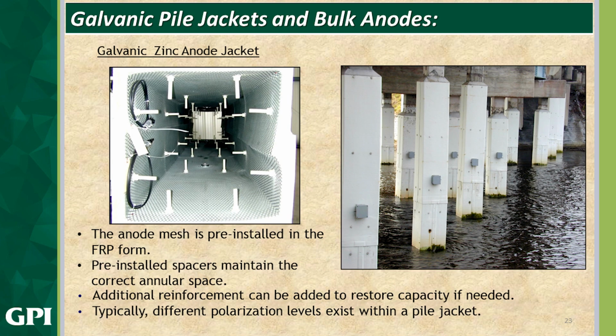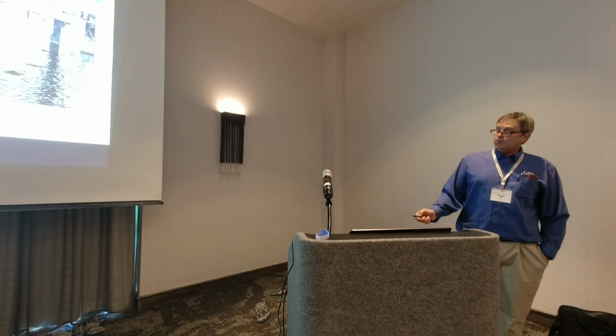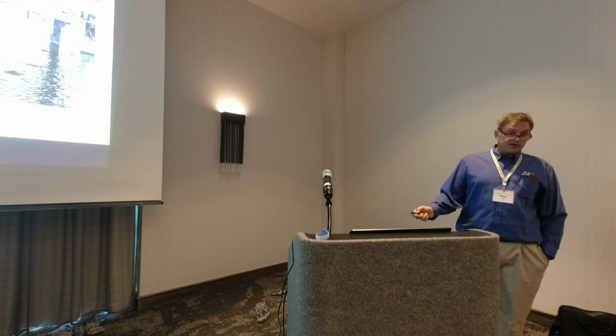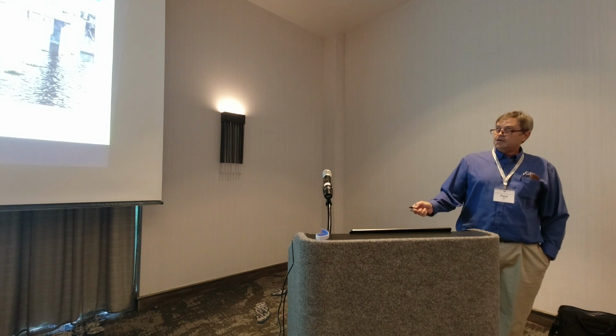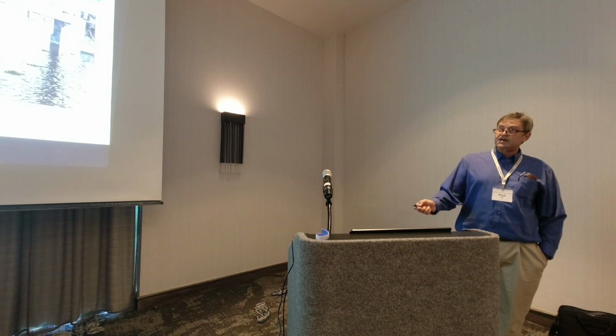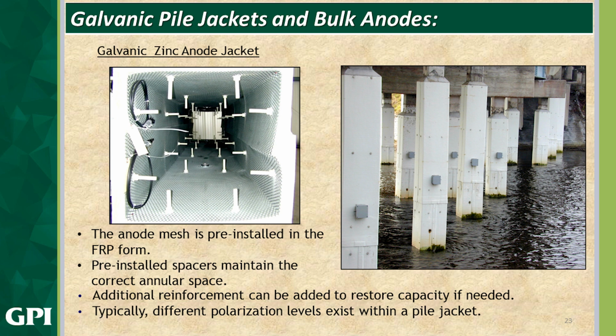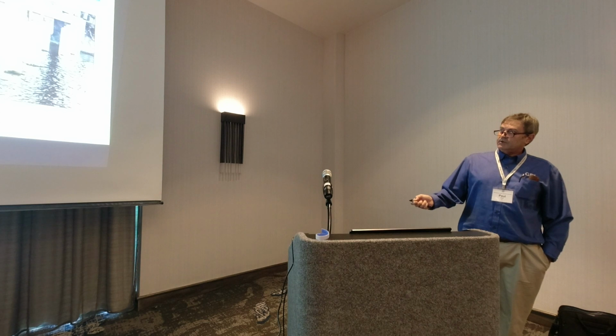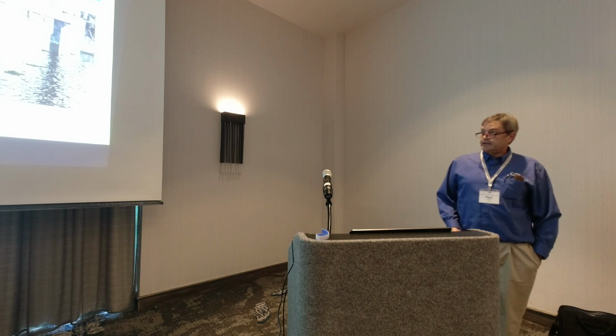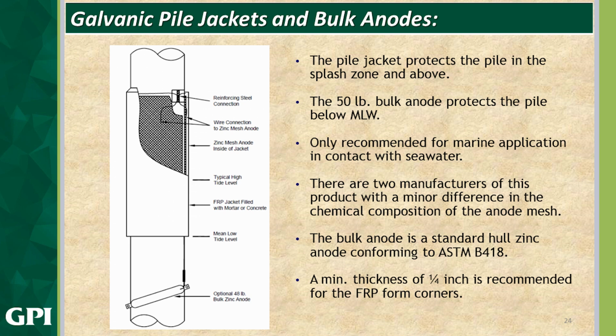So let's get a little deeper into the jackets, the pile jackets. Those are, at least from my experience, the workhorse of CP. What we've got is a fiberglass or polymer jacket. We've got either a zinc or titanium mesh, depending on whether it's galvanic or ICCP, installed inside the jacket. We've got spacers that maintain our annular space, and this is placed around the pile. We've got our monitoring box, and it's pumped full of grout. Here's more of a design drawing type sketch of it.